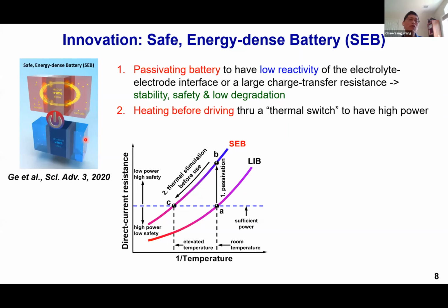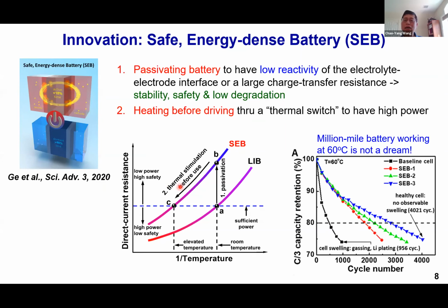But then right before you drive or use the battery, we can use a thermal switch to change it into the high power mode for use, right? So that thermal switch can be activated by heating. With that kind of very stable battery, you can achieve more than 4,000 cycles, and that translates to what was originally said to be a million-mile battery. But in our case, this is even a million miles operated at 60 degrees Celsius, right? Under a very harsh environment, we could still achieve million-mile batteries.